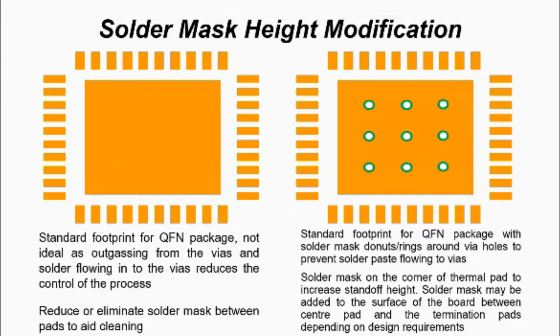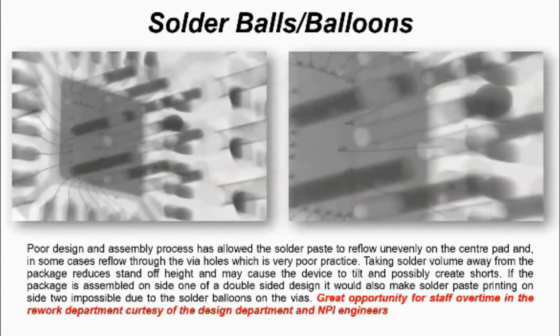If you can reduce the number of vias, then that also has an impact on our performance. Another thing that I have tried with one particular company is improving thermal performance of a package where temperature cycling was a concern, and actually generating standoff. And in this particular case, we put resist around the corners of the center pad. What effectively this is doing is increasing the standoff of the package, increasing the standoff of the solder joints, and then theoretically improving the joint reliability during temperature cycling. It's not something that's common, but certainly I've done it with one particular customer.